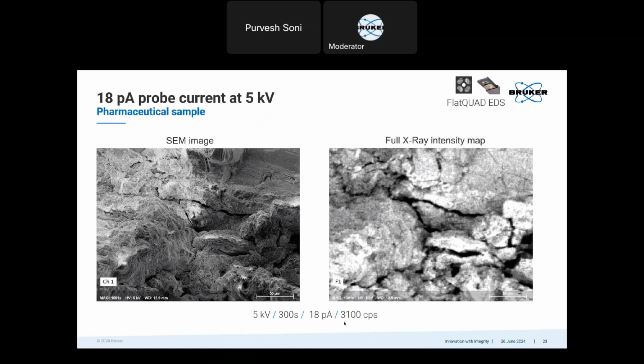I got high count rate of 3,100 counts per second, which is very good considering the very gentle probe conditions. And this is the full X-ray intensity map. So we can see that the sample is highly topographic, charging, and at a very low probe current, we still have a very filled X-ray intensity map. And yeah, there is barely any shadowing. There is only data which is missing from the cracks.